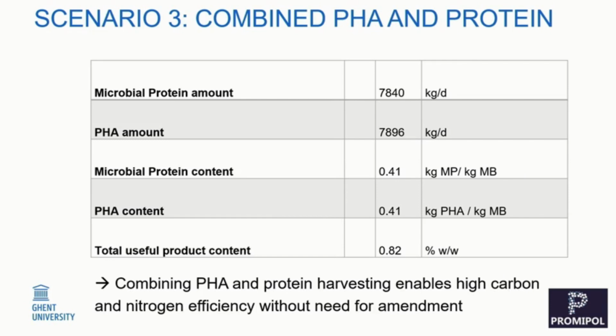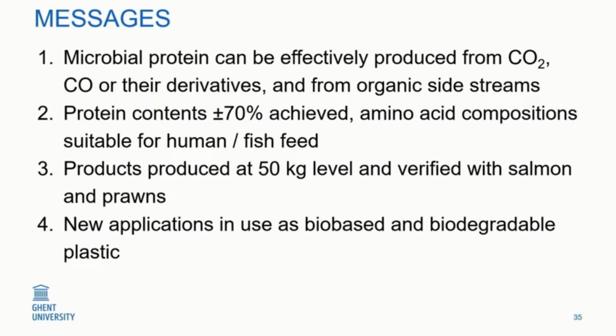If you allow, by developing new extraction processes, to harvest both the protein and the plastics, then your story is different. Because the cells grow, the cells accumulate PHA, and you harvest them both. So rather than having about 40% of useful product without amending that available organic stream, you end up with about 82% of useful product. This means that you use the organics from the wastewater at a carbon efficiency of about 82%. It's much higher. It's a different view of how you produce and how you look at your product. It's not just one product, you have to harvest 2 products, which is more complicated, but you use the feedstock much more efficiently.